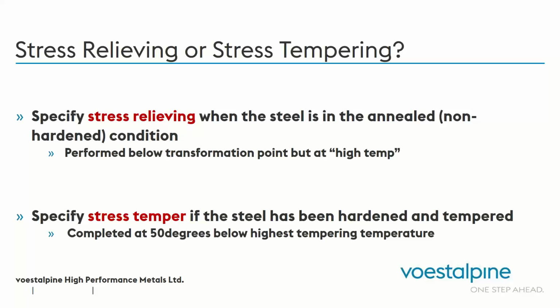Stress relieving is in the annealed state, and it's at a higher temperature. Higher is relative, but it's at a higher temperature than stress temper, and it's basically used to relieve stresses in the material. For instance, on large blocks before heat treatment or hardening processing. Okay, because you do get stresses in the material from machining, perhaps welding, and that can impact how the blocks perform in the quench process. If there's a lot of stress, they can crack.